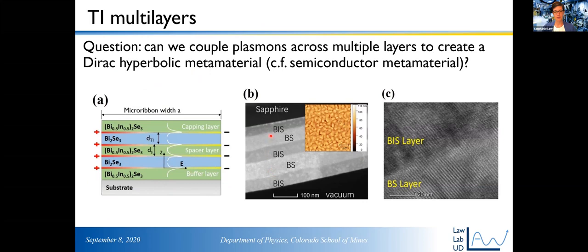This is the TEM image. This is an AFM image. I want to see it from the top. And a zoomed in TEM. So this is what we grew, four surface states. It's not really wavy like this. This is an artifact of the FIB.